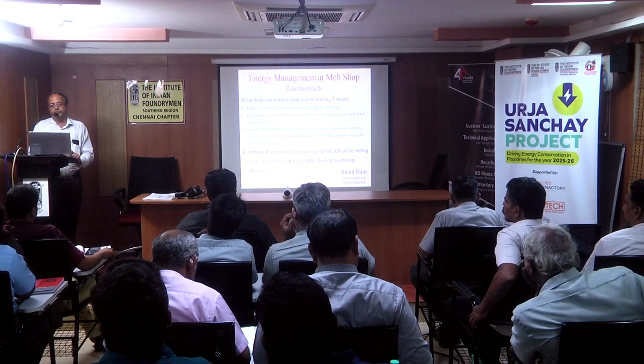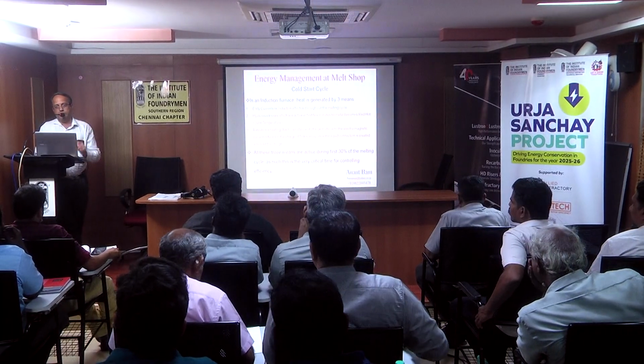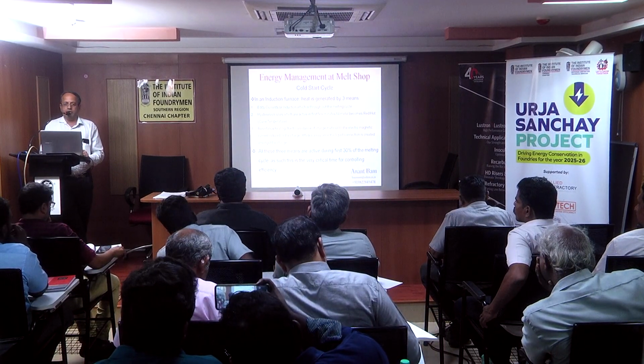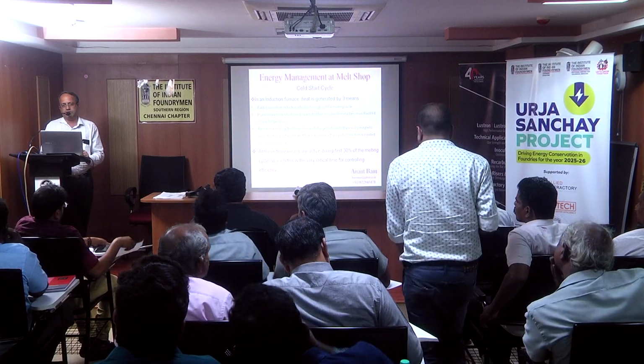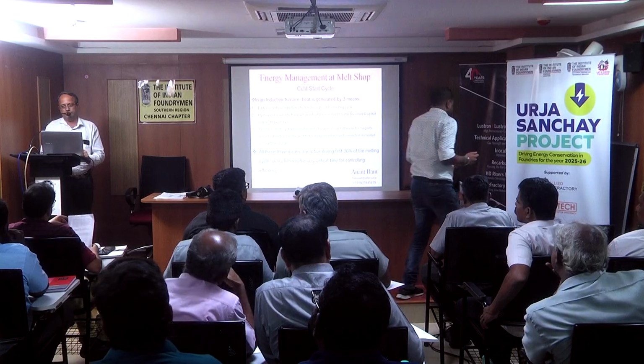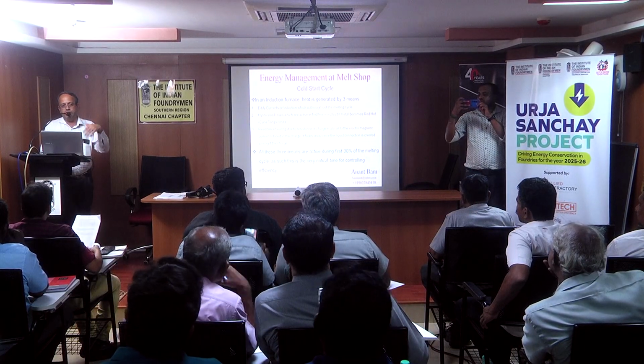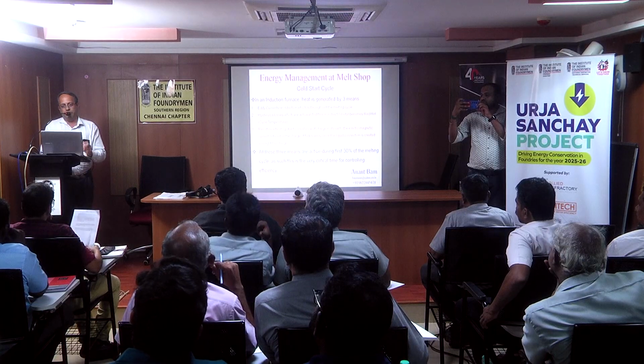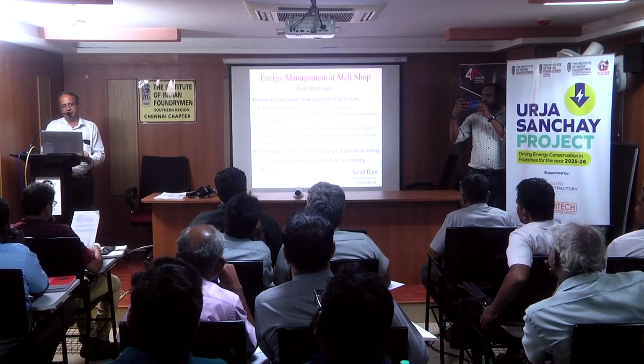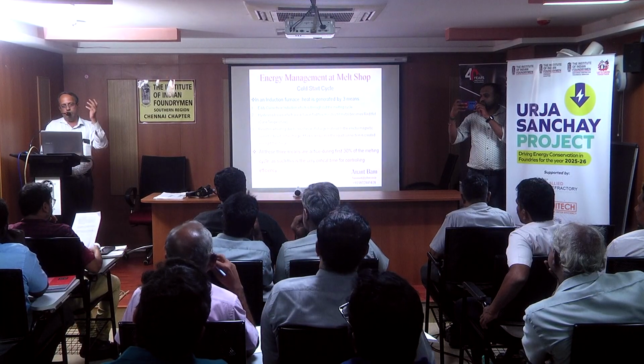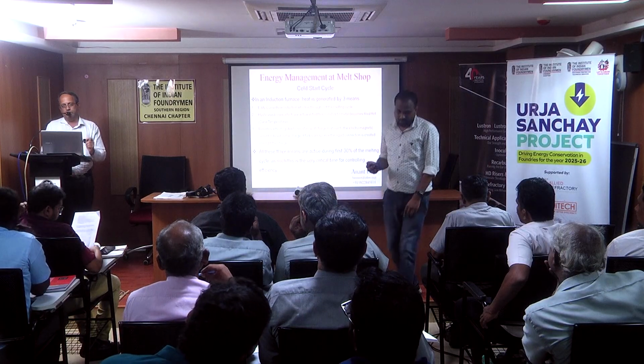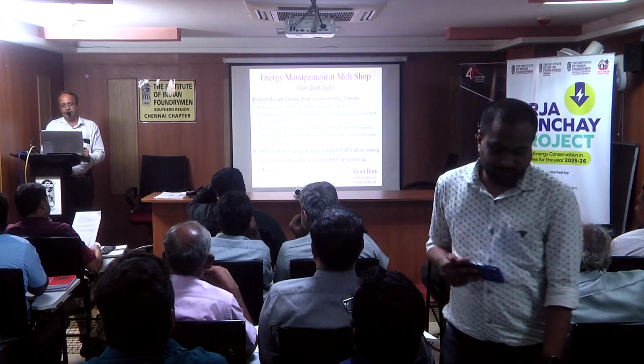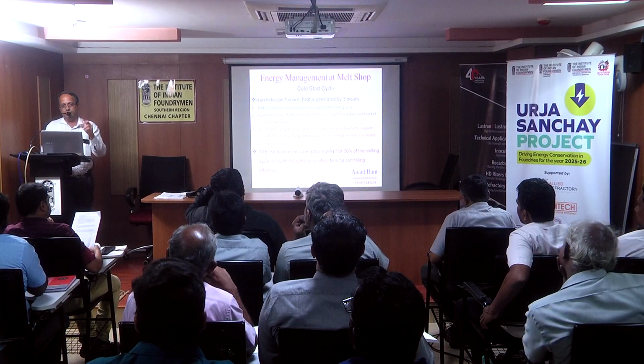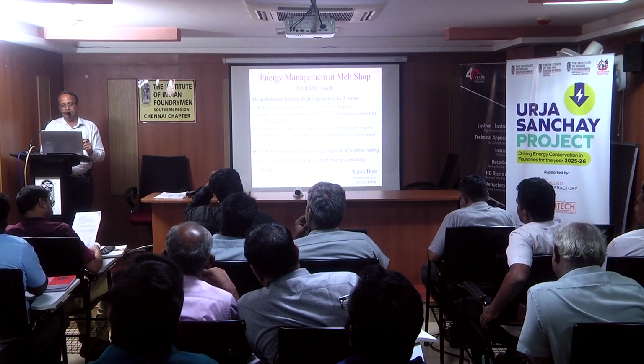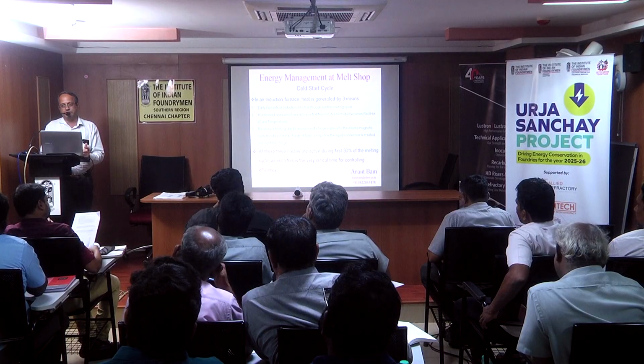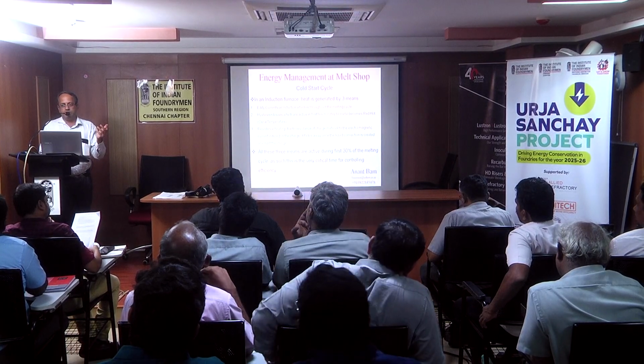Cold start cycle. Mr. Venkat will be talking more on it. But if you cool the furnace fast, the cracks developed are shallow. So it is ready to heat up fast, and your cold start cycle timing reduces drastically. As against that, if you allow the furnace to cool gradually, the cracks which develop are quite deep. So those cracks take a longer time to seal. Naturally, your cold start cycle timing increases. Again, that's a time loss and energy loss.